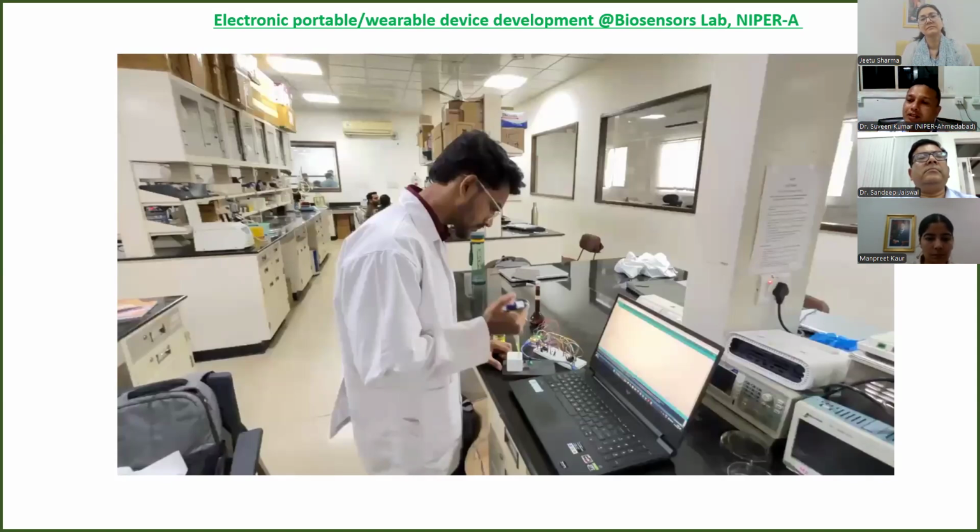How will it occur? It will occur when you have used controlled size. If you use 10 nanometer, it will be electrophoretically deposited onto the surface, and it will give a smooth surface. But sir, if some part is 10 nanometer, some is 100 nanometer, you can obtain this type of surface. One part is 100 nanometer, another 10 nanometer, 300 nanometer, again 200 nanometer. So if you can control the size of the nanoparticles, electron transfer is smooth. If your transfer is smooth, you can obtain a reproducible result.